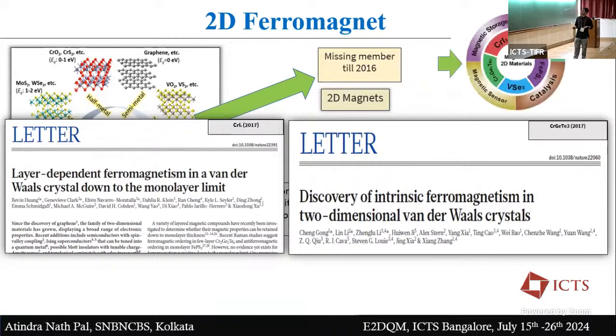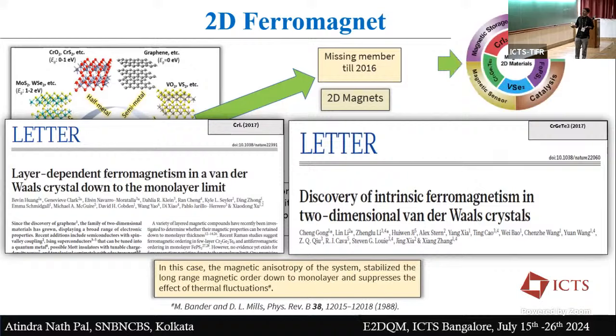And the reason behind this is that magnetic anisotropy plays a key role. This stabilizes the long-range magnetic order down to the monolayer and suppresses the effect of thermal fluctuations. And this has created a lot of possibilities. After that, a lot of new materials came, like CrI3, CGT, VSe2, and FePS3.